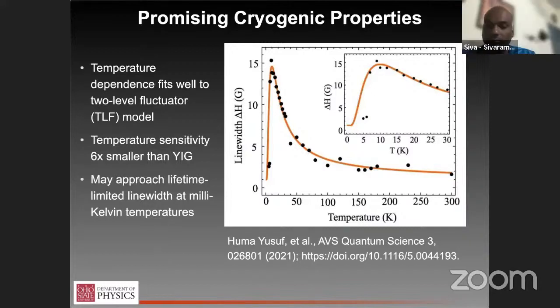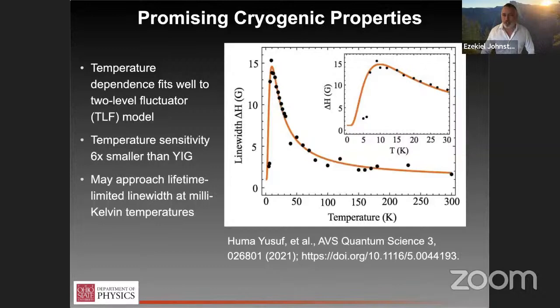He was working with this molecular-based magnet, and so we just sort of started working together, in a more traditional spintronics context. So I think the first paper we published was using the V[TCNE]x as a magnetic electrode for a 3-5 LED structure to do what's known as a spin LED, which is one way to measure the spin polarization of a charge current. And so we got that working, which was surprising, and I believe a first at the time of being able to extract a spin polarized current from a molecular based system.